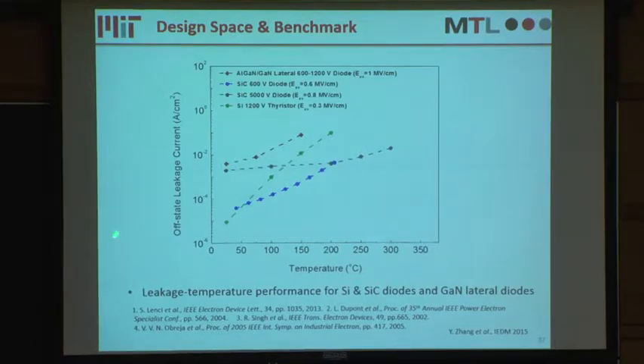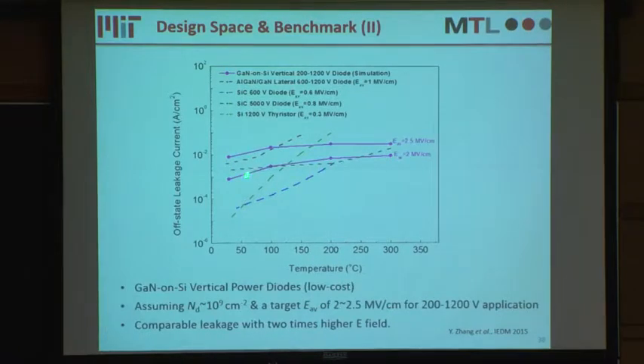So here we plot the off-state leakage current as a function of the temperature, and here's the experimental data for all the other power devices. This group of pink lines represents the design space for the leakage current of the gallium nitride on silicon vertical devices. So basically from here, we can see the gallium nitride on silicon vertical device can have a comparable off-state leakage current, but with two times higher electric field.